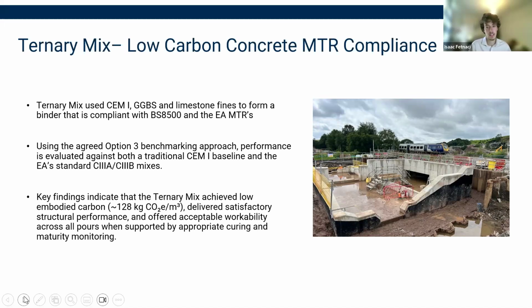Key findings indicated that the ternary mix achieved a low embodied carbon, roughly 128 kilograms of CO2 per cubic meter, which is a massive reduction over standard CEM I concretes and other concrete mixes. It delivered a satisfactory structural performance and offered acceptable workability across all the pours on the project, when supported by curing and maturity monitoring. So it was a very successful deployment of ternary mix on the project. So thank you, and now over to the MMC theme.